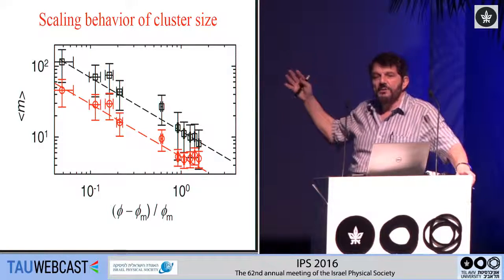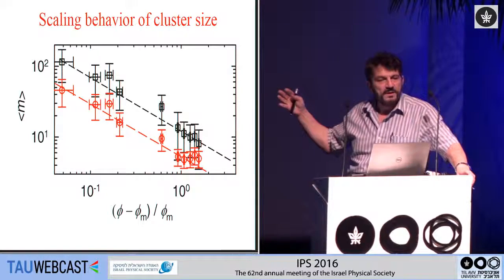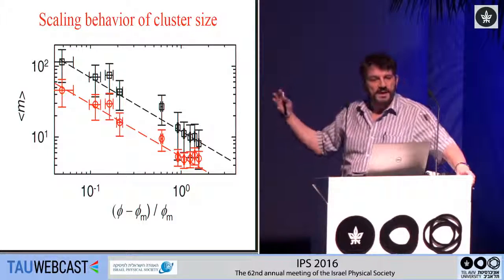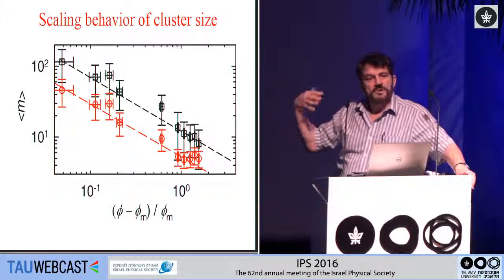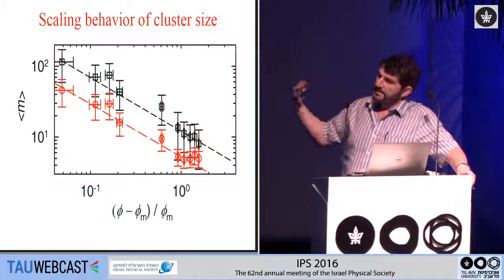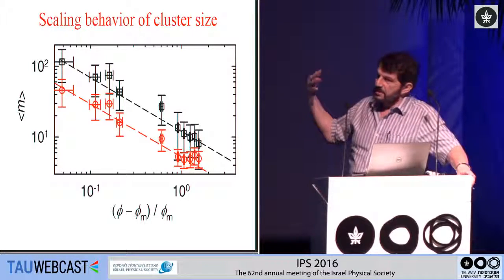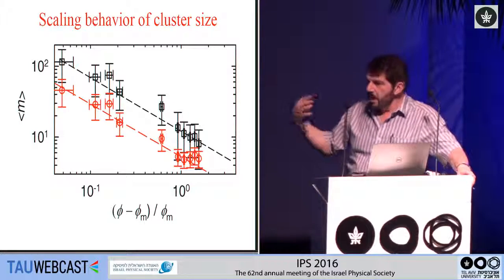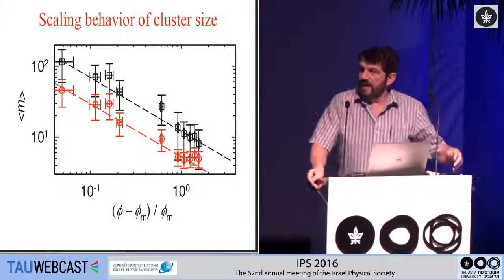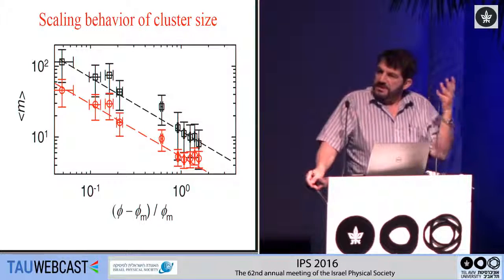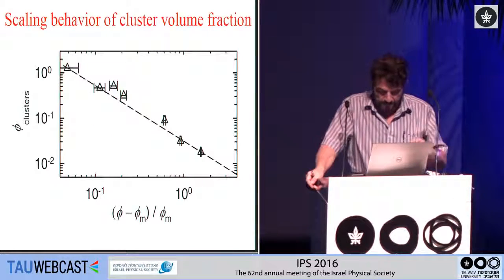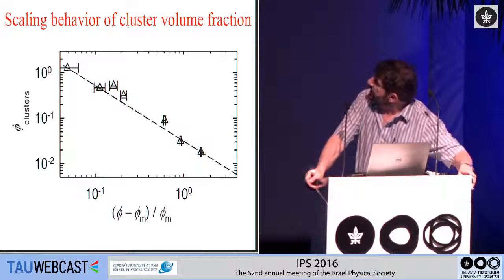Well, what does a power law distribution remind you of? It reminds you of a critical behavior. It reminds you of some critical transition. But remember, this is melting. Melting in 3 dimensions is normally not thought to be critical. It should be first order. Nevertheless, you see this critical-like behavior. In fact, you see it in other ways as well.